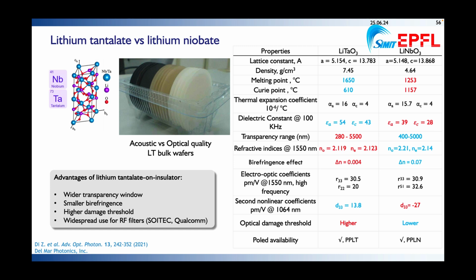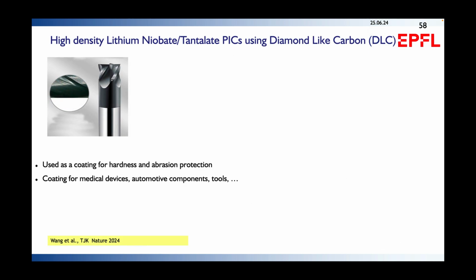There's a material called lithium tantalate, which has almost exactly the same properties as lithium niobate. So why was lithium tantalate not used for optical modulators? It wasn't used because titanium indiffusion in this material occurs at a much higher temperature, and that's why lithium niobate was favored. But the material has lower birefringence, higher damage threshold, and a wider transparency window. On top of this, the material is used commercially in Wi-Fi. In fact, your phone may already use lithium tantalate filters for 5G, 6G, which require higher K-squared for the larger passband. And so the question is, how can you etch lithium tantalate or lithium niobate?